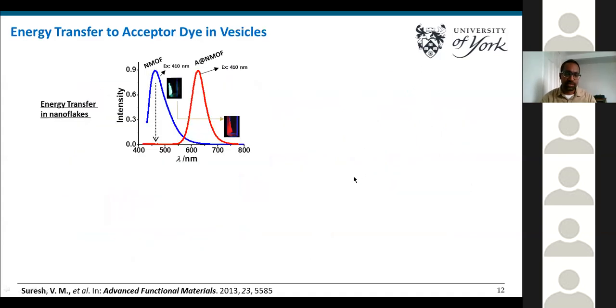So we indeed see such a phenomenon happening in the dye-loaded MOF. The red spectrum is the emission spectrum of the dye-loaded MOF, excited at the MOF's excitation. When it is excited at the MOF's excitation, we are supposed to see MOF emission. Instead, we see no emission in the MOF region, but we see a strong emission at 625 nanometer from the dye molecule. This is an indication that the energy used for exciting the MOF has been transferred to the dye. As we also see, the color of the emission has changed from cyan to completely reddish.